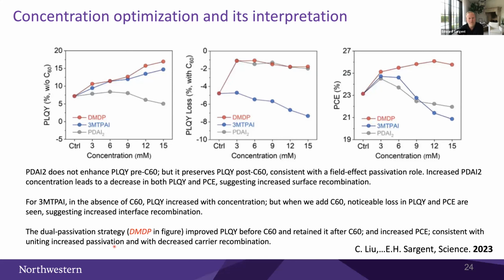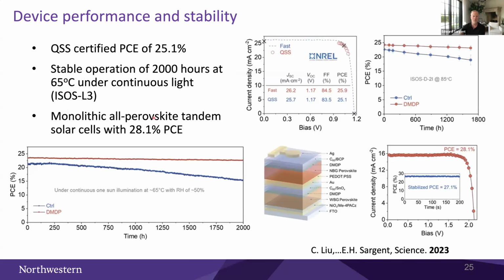decreased carrier recombination. In terms of devices, this enabled a QSS certified PCE of 25.1%, a stable operation over 2,000 hours at 65 degrees C in the ISOS-L3. And it also enabled us to report some interesting all-perovskite tandems a little bit above 28%.